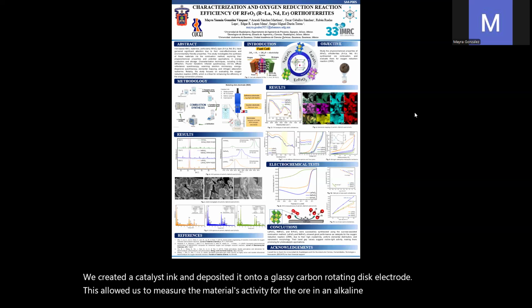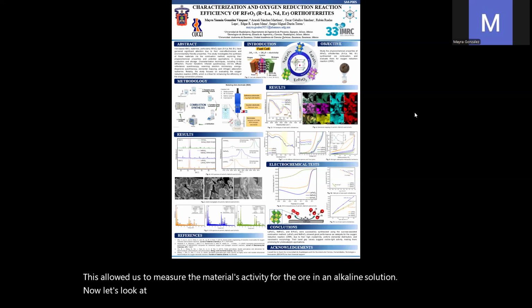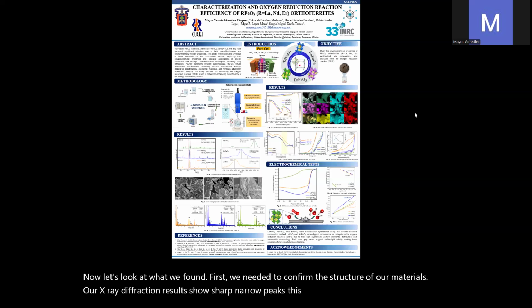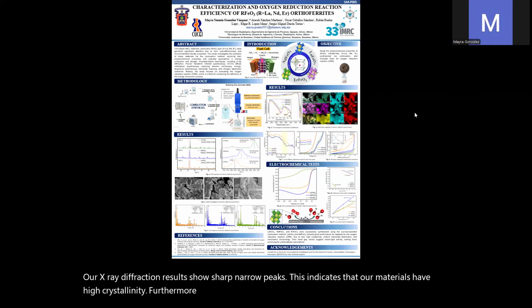Now, let's look at what we found. First, we needed to confirm the structure of our materials. Our X-ray diffraction results show sharp, narrow peaks. This indicates that our materials have high crystallinity. Furthermore, the absence of extra peaks confirms that we successfully synthesized pure materials with the desired orthorhombic crystal structure.